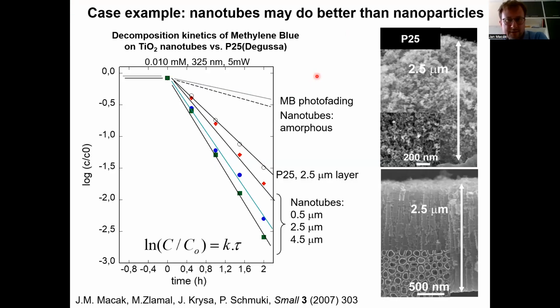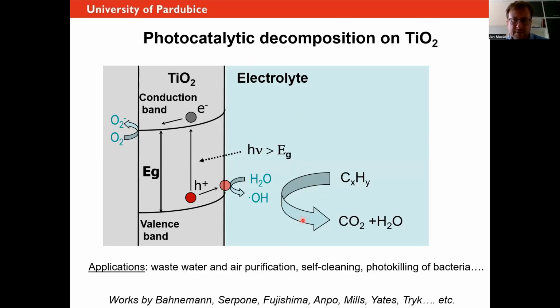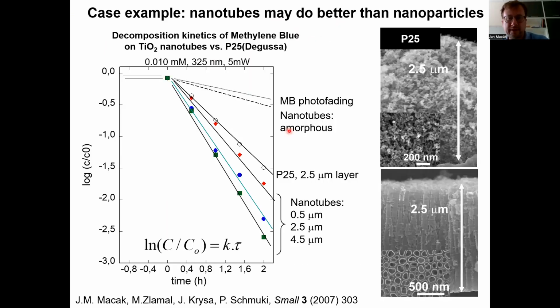And this here is a slide showing some pioneering study we made some time ago. It was a pioneering study where we showed a comparison of the photocatalytic performance of tubes compared to nanoparticles. So the photocatalytic experiment is actually shown here. Usually you do it with some kind of model dye. So it has a color, and upon the photocatalytic reaction, the color is removed. So it becomes actually transparent. And you measure by UV-vis spectrophotometry the color of the dye in time of the photocatalytic reaction. And when doing so, you actually measure the decay of the dye.